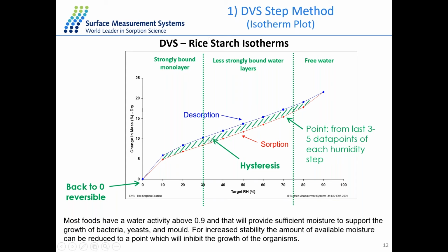And this is also confirming with the hysteresis gap between sorption and desorption. So the gap here is just showing that when the water molecule diffuses from the bulk to the surface, it has a different kinetics. So the desorption is a diffusion limited process that results in the hysteresis gap between sorption and desorption.